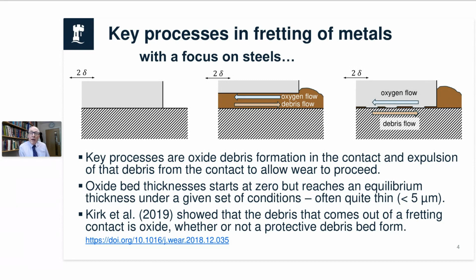And to allow that to happen, therefore, we need to be getting oxygen flowing into the contact and debris flowing out of the contact. And the reason I say that debris must be coming out is because what we also find is that the oxide thickness, if it does form, tends to not grow very large. However long you leave the test for, we've run tests quite often out to 10 million cycles, we find that a 5-micron debris bed will develop in maybe the first 100,000, and then it stays at about the same thickness forever. So we obviously reach some form of equilibrium within that system.